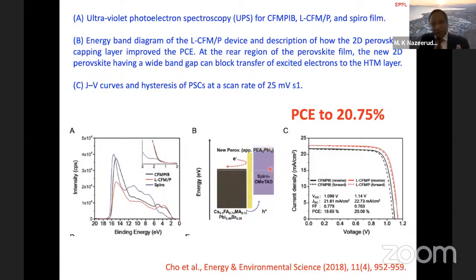So what is happening here is when you shine light within the perovskite, you create charges, and the positive charges are extracted through the two-dimensional perovskite because the HOMO levels of the three-dimensional perovskite and the two-dimensional perovskite are well aligned. However, the LUMO level of the two-dimensional perovskite is significantly above the three-dimensional perovskite. So the electrons which are generated within this perovskite come to this site and they turn away towards the ETL layer. On the contrary, the positive charges are extremely efficiently extracted into the hole-transporting material.